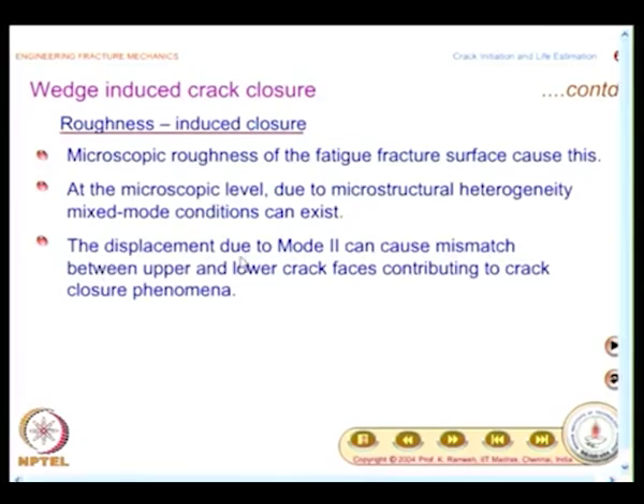So, do not come and say why you put the crack faces as jagged. At such high magnification, even a straight edge would appear jagged only. So, you have to look at it, these are not macroscopic pictures, they are highly magnified microscopic pictures. And what is mentioned is the displacement due to mode 2 can cause mismatch between upper and lower crack faces, contributing to crack closure phenomena.